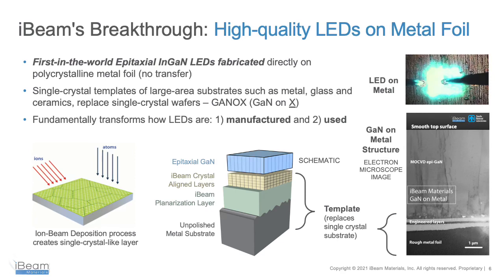Well, this is exactly what iBeam Materials' breakthrough is. We were able to develop a revolutionary new process where one does not need a single crystal wafer for deposition of epitaxial indium gallium nitride LED materials. For the first time in history, high-quality epitaxial opto-semiconductors are deposited directly on a non-single crystal substrate.